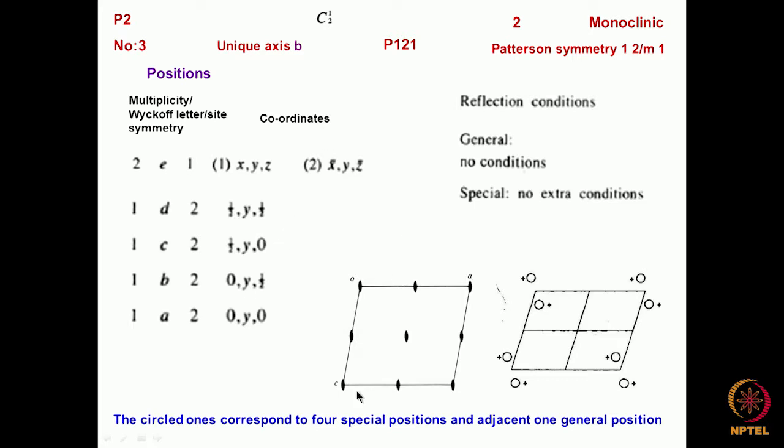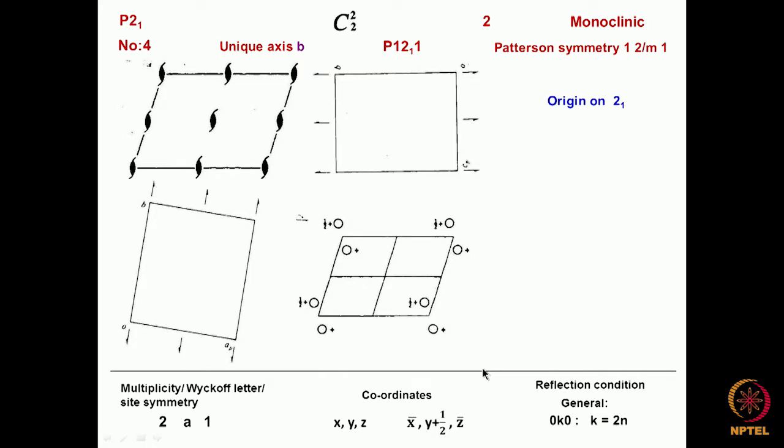When we have the unit cell and we know the symmetry associated at different points, then by putting atoms or motif at some of the symmetry points or on a general point, in short anywhere within the unit cell, we can determine what positions atoms have to be generated so that the structure will show twofold symmetry, right. This is what essentially is being shown, the various points.